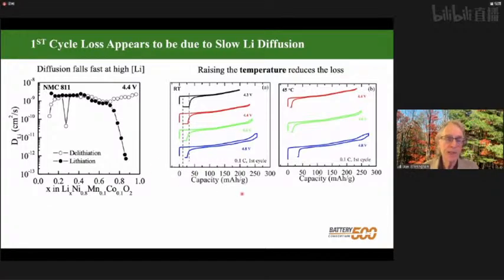So to double check diffusion was the culprit, we actually looked at the behavior at a couple of temperatures. Here is room temperature, charged to different voltages, and you can see the capacity increases. You get more and more lithium out the higher the voltage you go to. Clearly 4.2 volts is too low to be of interest. At 4.4 volts, you notice the charge and discharge go right on top of each other. But at 4.6 volts, they're starting to separate, and at 4.8 volts, they're separating even more. This is because we're now getting side reactions and resistive species on the surface. So we don't want that.